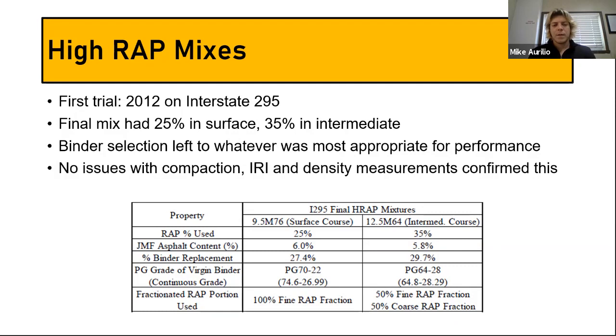All right, and you can see here, if I go back to the binder selection, the surface course was at 25%. New Jersey's typical binder grade for a highway like this would be a 70-22. So even at 25%, they didn't soften the AC the way I think we would have automatically done here. Part of the way they accommodated for the RAP was that 1% VMA increase and the extra AC content. Okay. You can see in the intermediate course where they went to 35%, they did in fact drop the binder grade.